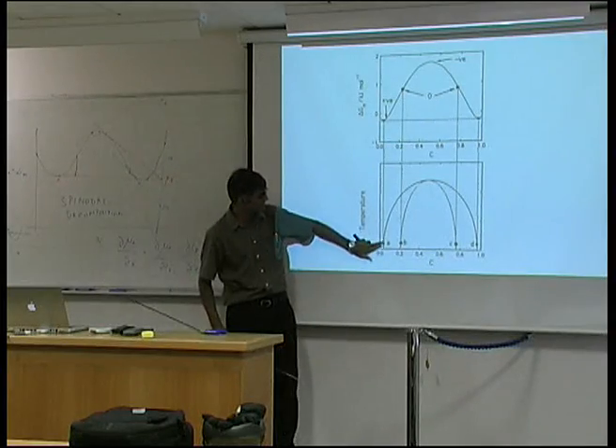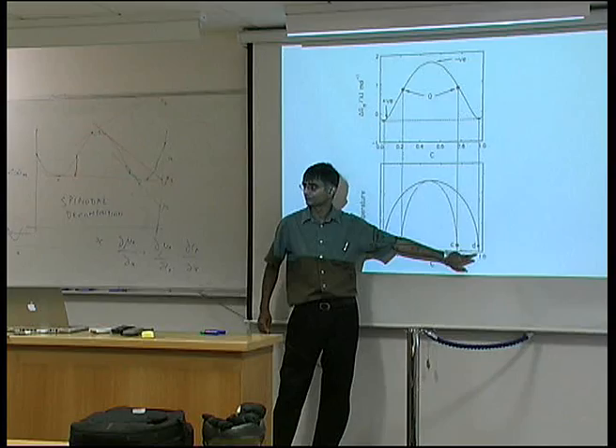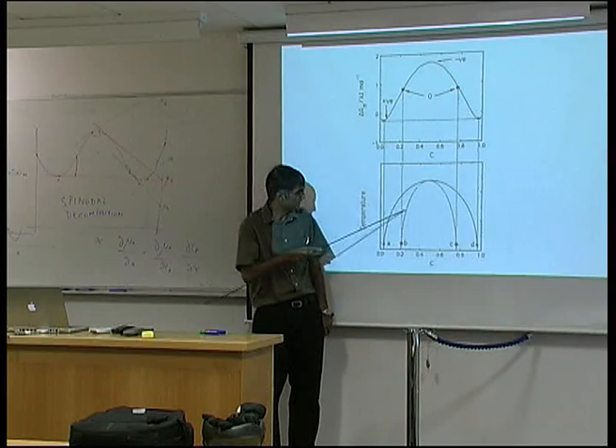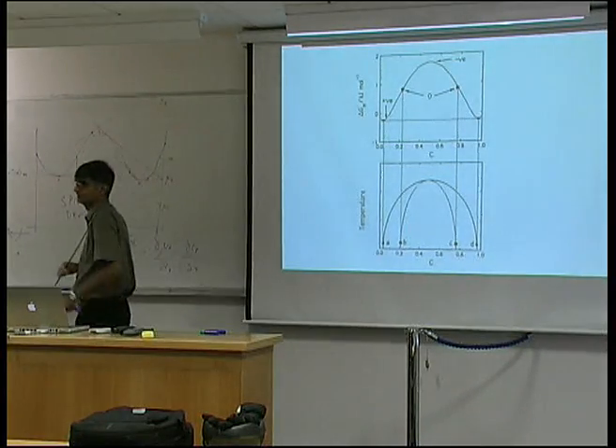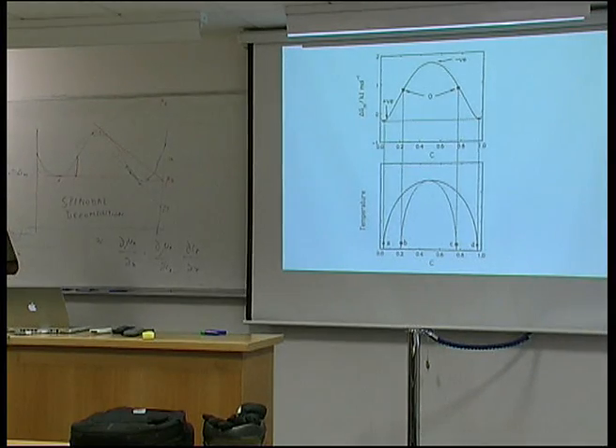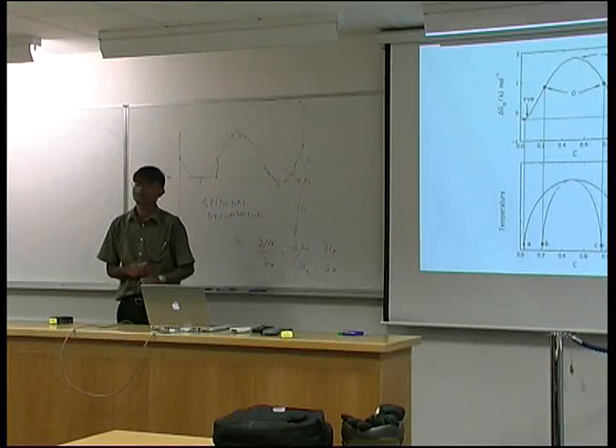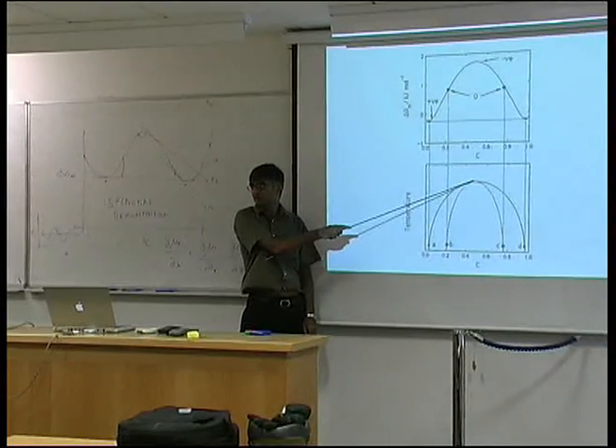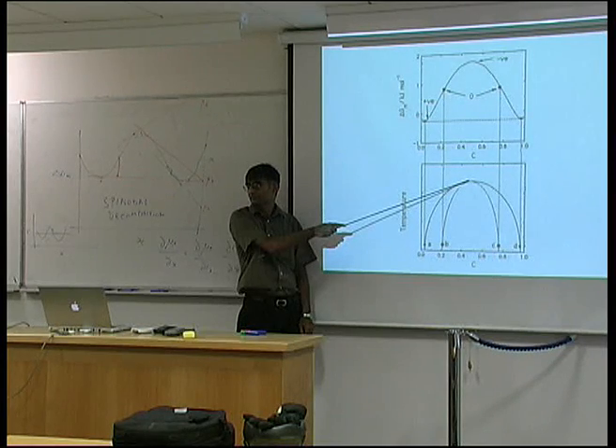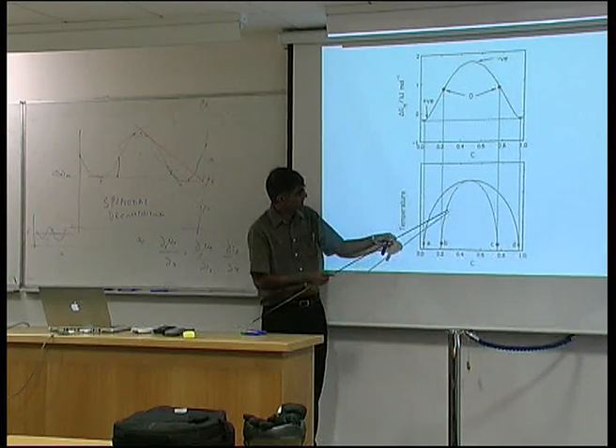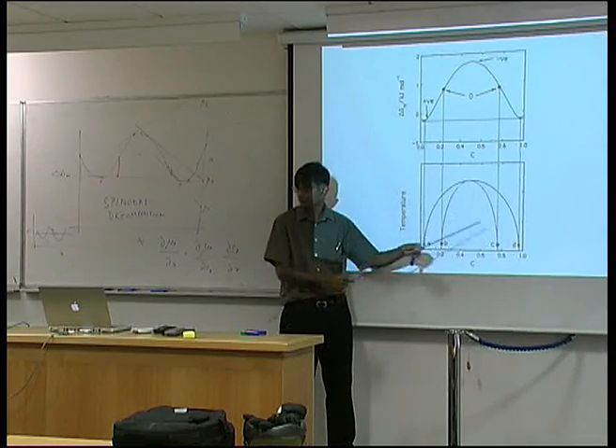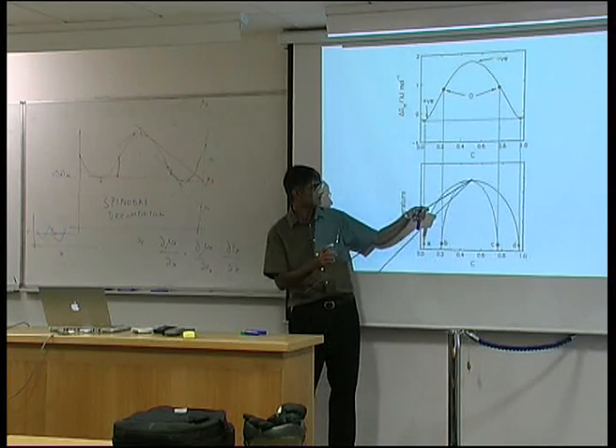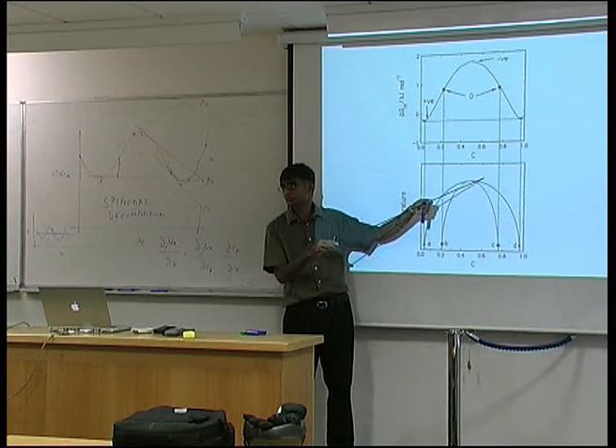This is the curve you would normally find on a phase diagram. A single solution would not be stable if it lies between the points a and b - it may require nucleation, but certainly there would be a reduction in free energy. At some point, a single solution becomes favourable. Why does this disappear at a certain temperature? Because entropy wants everything to be mixed up.